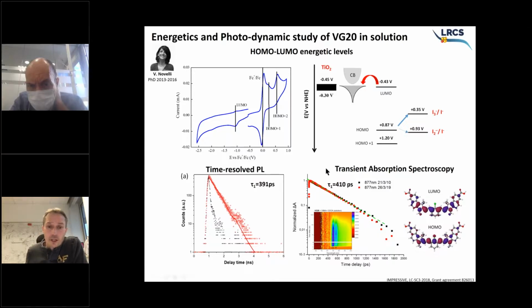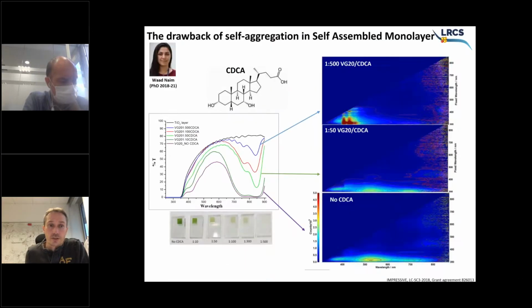Here we have 400 picoseconds, which has also been confirmed by another technique, transient absorption spectroscopy, showing exactly the same results, meaning that the excited state lifetime is very, very short, and then you really need to prompt the electron injection before the dye decays itself and gives luminescence in the devices.